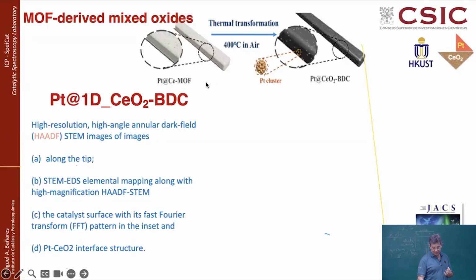BDC is benzene dicarboxylate. It's a very simple ligand. You make structures where you get this cerium benzene dicarboxylate, and we prepare it mixed with a platinum precursor. And then when you make the calcination, this porous metal organic framework goes into a porous oxide network, where you have the ceria closely interacting with platinum.